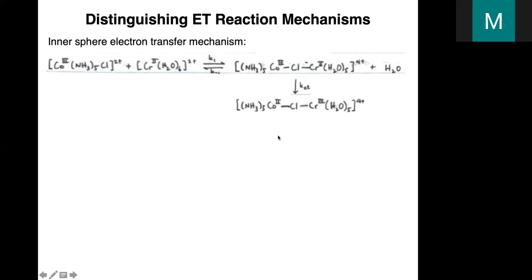And once that electron transfer has occurred, let me point out, this initial complex where we haven't done the electron transfer is called the precursor complex. And the species that you get immediately after the electron transfer would be the successor complex. And once you form the successor complex, we can note that now the lability has changed. So initially, cobalt(III) is inert and chromium(II) has labile ligands. But after the electron transfer, that situation is swapped. Now chromium(III) is inert and cobalt(II) can substitute ligands rapidly.